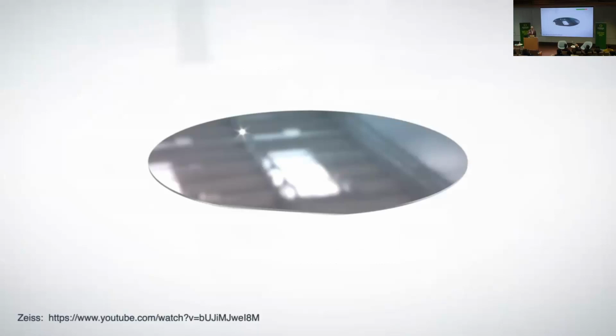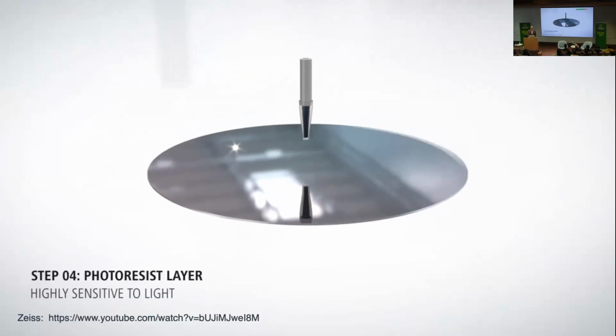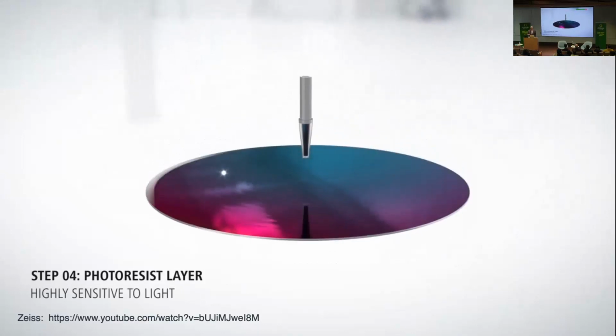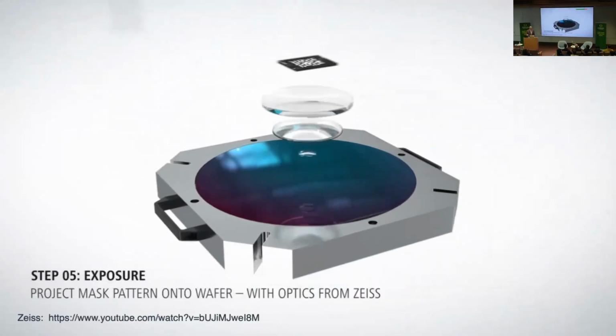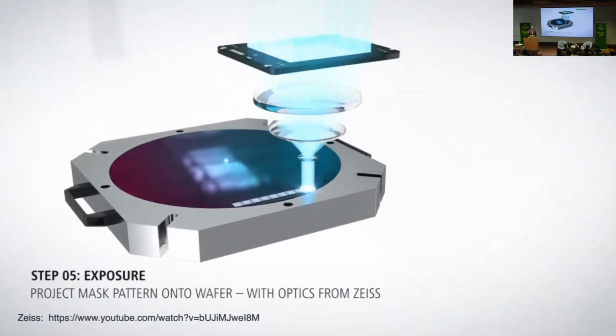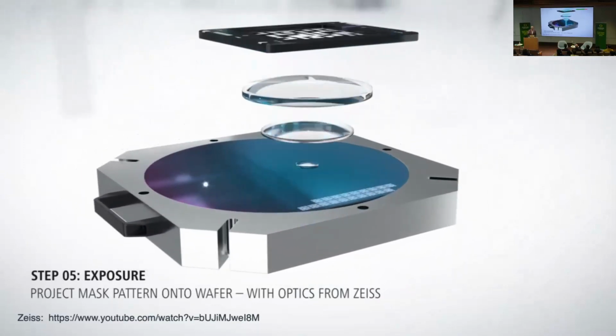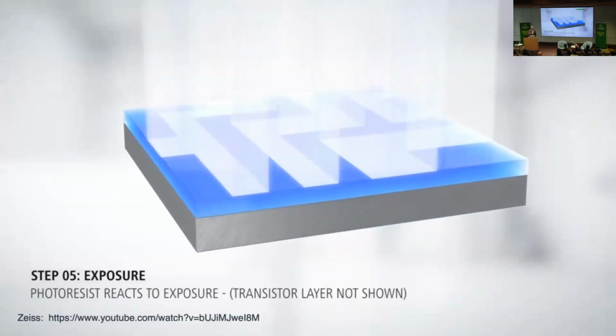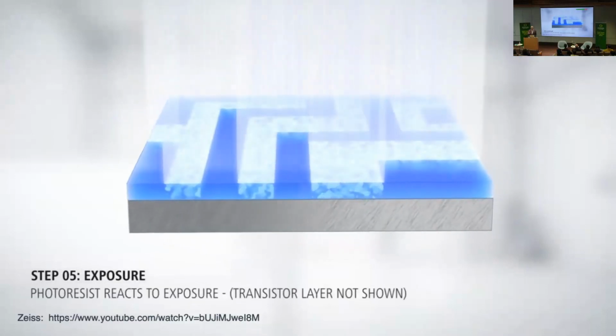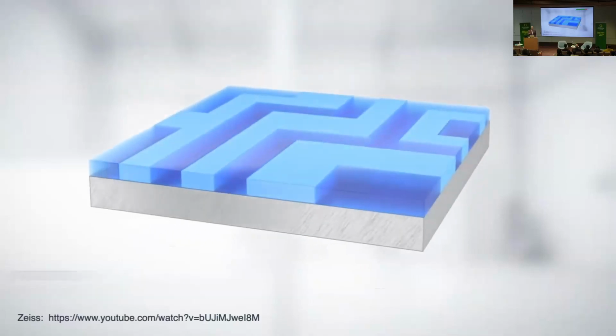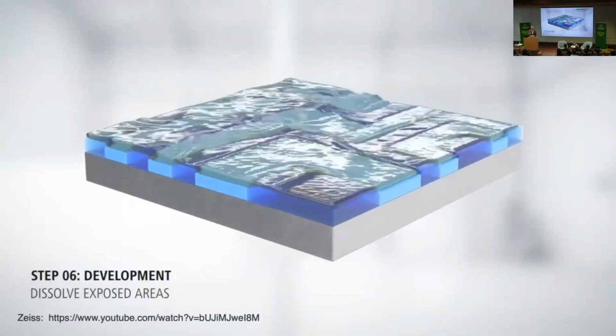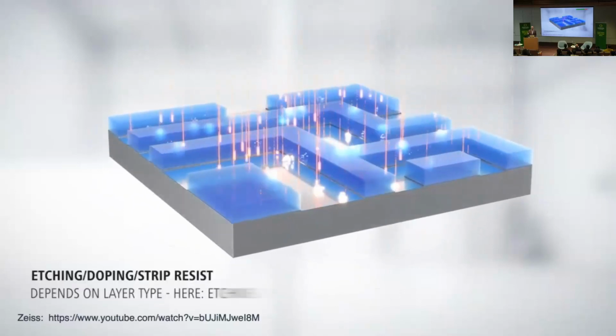Let me review this process with you and see how it relates to the topic I'm going to talk about. This is a silicon wafer, and it starts with dissolving a polymer in an organic solvent, typically, and pouring that polymer onto a wafer that's spinning at a high rate of speed: spin coating. The solution spreads out, the solvent evaporates, and it leaves a thin film. Then you pass light through a silhouette, and where that light hits, it induces a chemical change in the polymer. That change often alters the solubility characteristics, so you can come in with a solvent, remove certain areas where the light hits or doesn't hit, and a pattern develops.